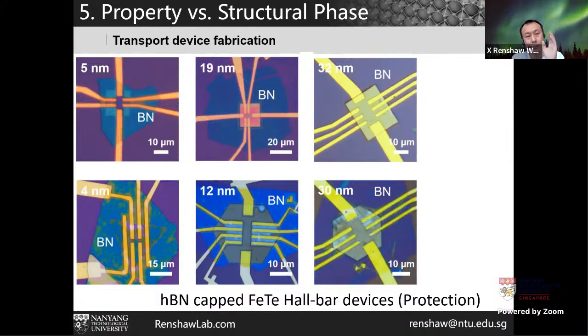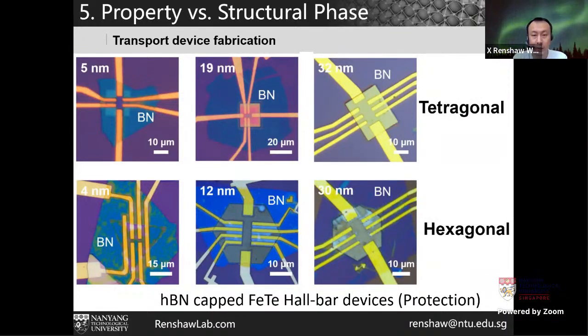We have these devices on both the tetragonal phase and the hexagonal phase. Of course, we use BN, which is another 2D material, on top to protect the device, because as I said, the sample is not super stable in ambient conditions. So we fabricate the device in the glove box, we put the BN on top, and then we do the measurement. This one on top is the tetragonal phase, below is the hexagonal phase.